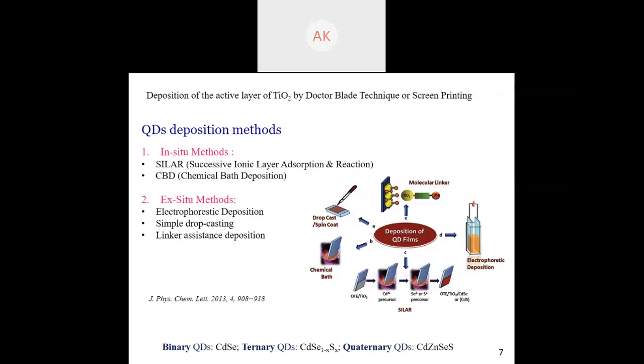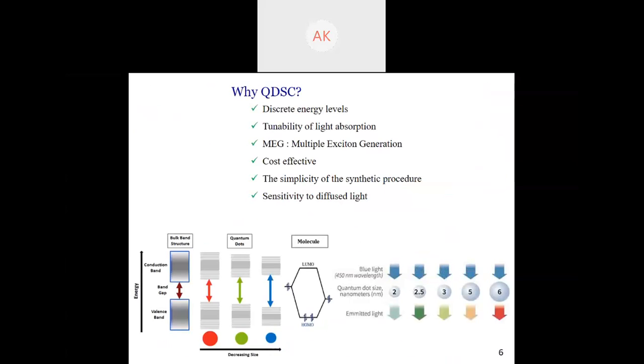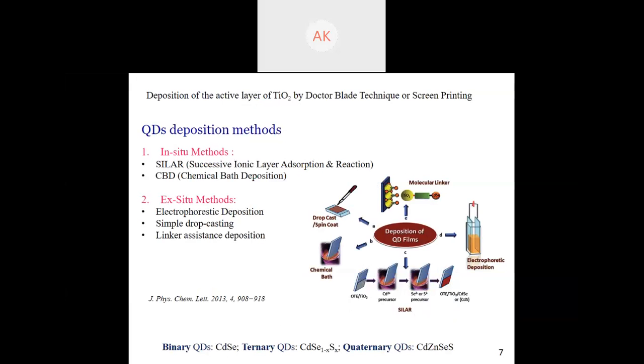Some labs prefer ex situ techniques because, as I talked about in my previous slide, size control is such an important factor in quantum dot sensitized solar cells, because it will have a check on the emitted light. So some labs prefer preparing the quantum dots previously by hot injection method or hydrothermal method and then depositing them. But if you want to make hot injection quantum dots, you have to have real setups in the lab, like Schlenk lines and a proper inert atmosphere glove box. So if you have these techniques, please go ahead with an ex situ method, or you can also compare the two. I hope I have tried to answer your question to the best of my abilities.